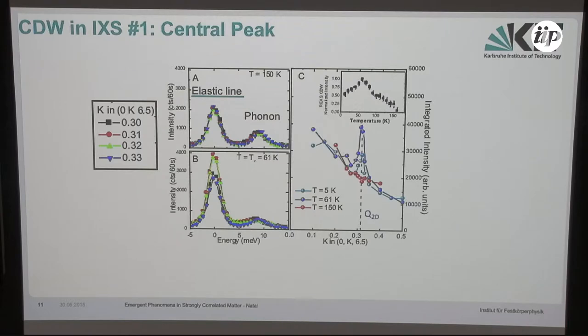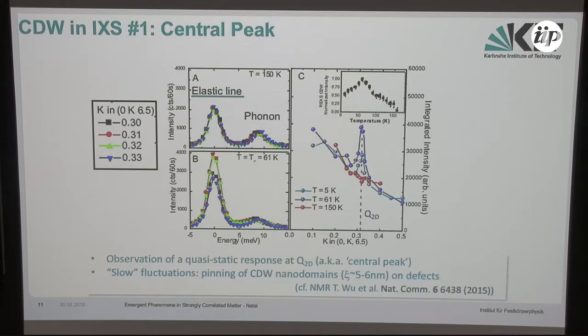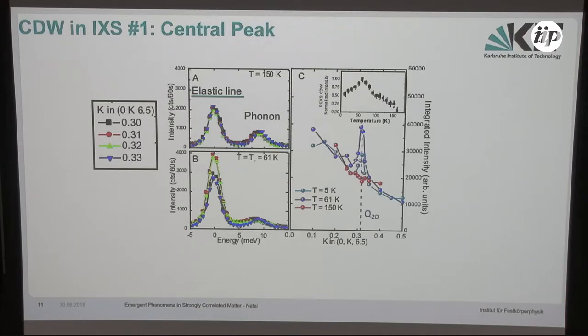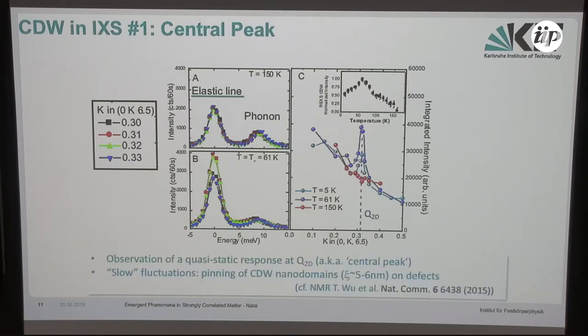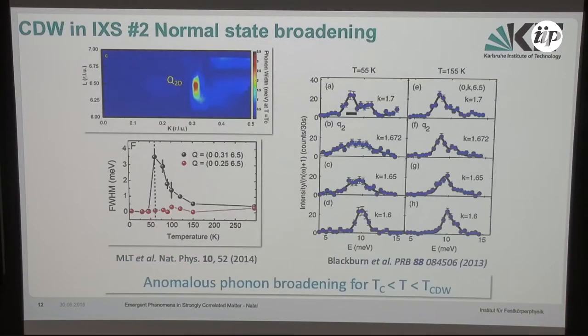The first thing that we see when we cool down into the CDW state is a big enhancement of the elastic line. If I plot the elastic line intensity as a function of momentum, I see a peak. That's basically a highly static signature of our CDW. It shows us that the signal that we see in the diffuse scattering is mostly elastic and therefore static. That's what you call the central peak. It's well known from classical transitions, and it basically tells us that we are dealing with some kind of either pinned domains or slowly fluctuating domains.